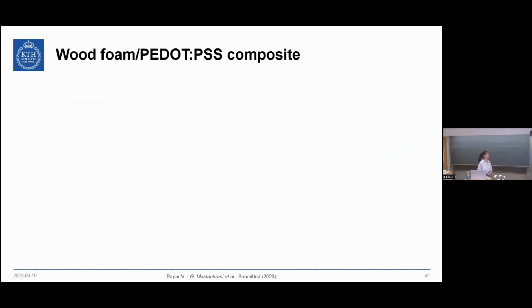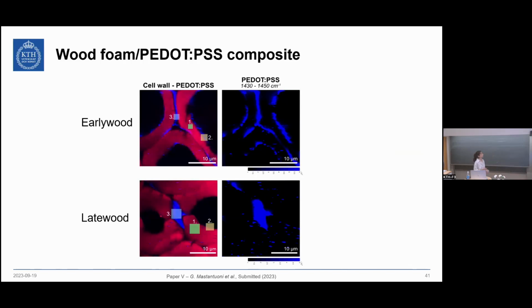So what happens when we try to introduce PEDOT:PSS? We could see from Raman spectroscopy, where PEDOT:PSS is represented in blue, that we have the presence of the polymer again in the middle lamella and on the top of the lumen surface, as in the previous studies. But we could also see a lot of dots representing the polymer inside the alveolate cell wall structure that we have created, so this alveolation is actually big enough to host a polymer that in this case was around 30 nanometers in diameter.